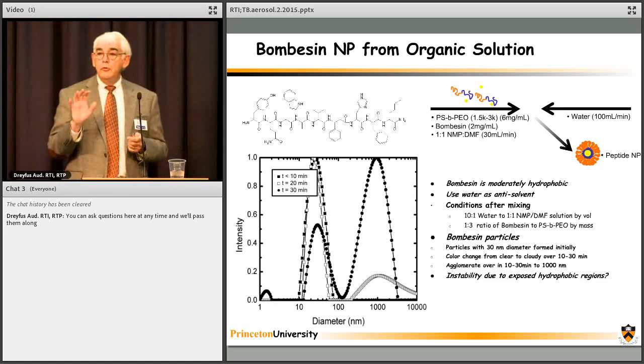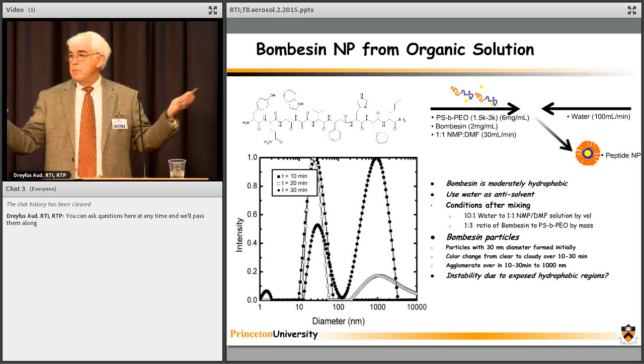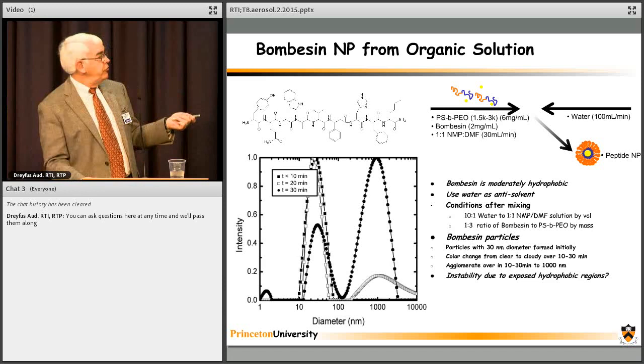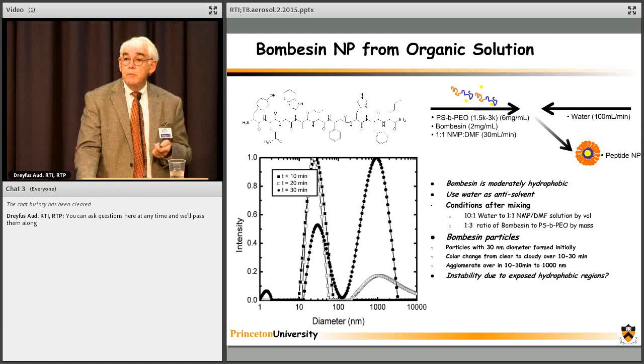Most instability is, I made particles and they just aggregated non-specifically to big junk that falls to the bottom of the test tube. This is not a non-specific aggregation. This is a rearrangement to a new object, which is, for this particular case, 1,000 nanometers in size. So what's going on? Why does this go away and what happens? Why does it stop at 1,000 nanometers?